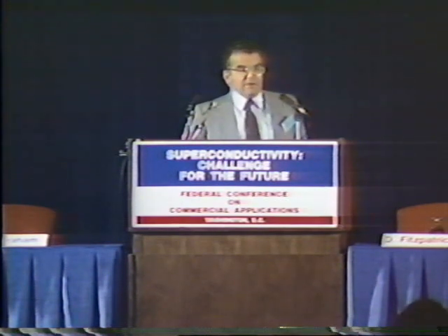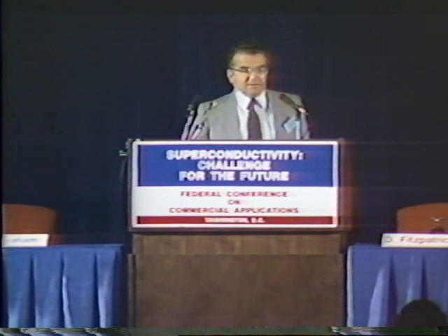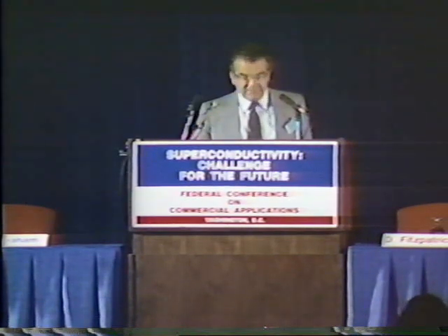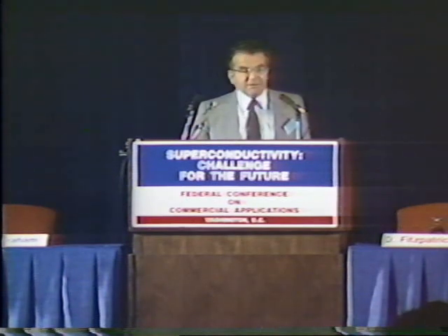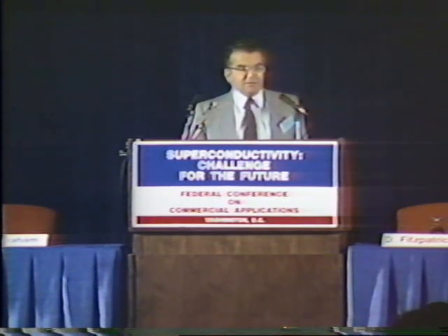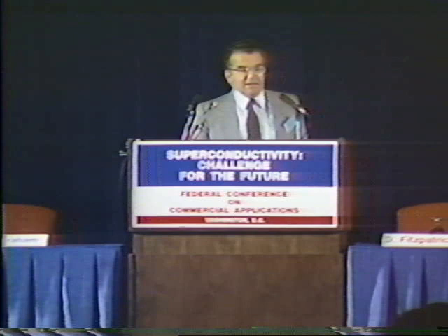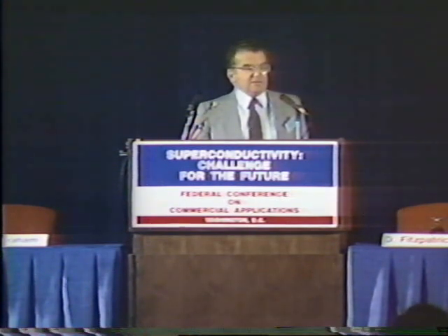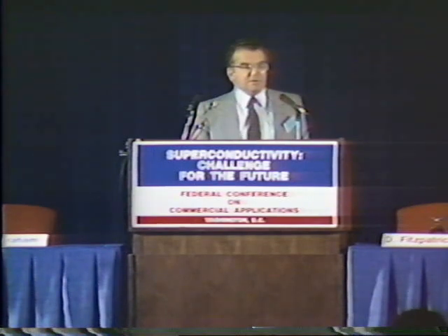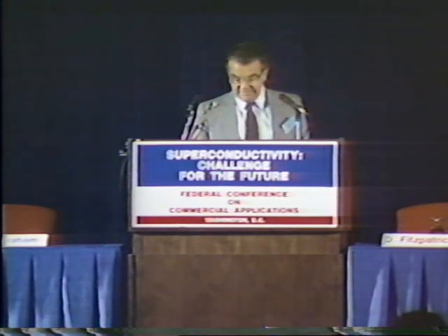So you can prepare films with this kind of required critical current density, but let me tell you that strontium titanate is by no means a practical substrate for any electronics application that I know of. It has an enormously high dielectric constant. Propagation of signals on strip lines on strontium titanate would be slow, so slow that nobody would consider using it. That's on bulk strontium titanate.